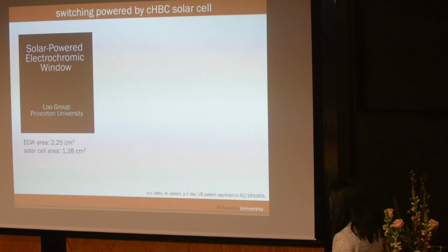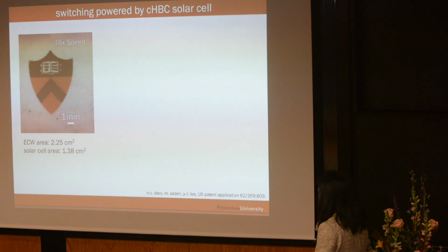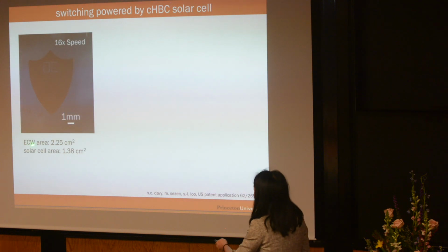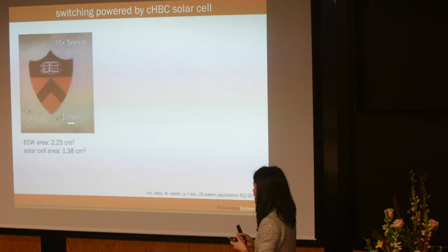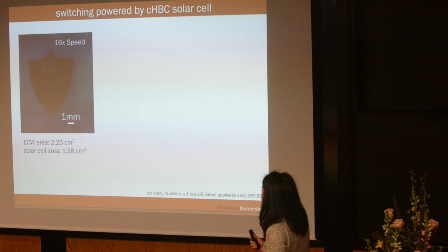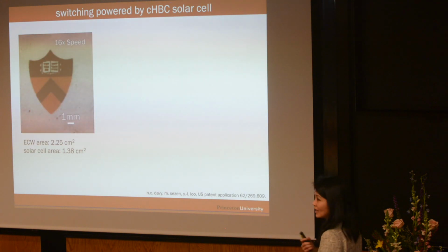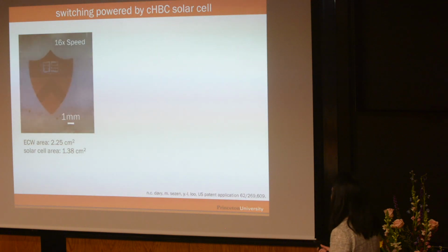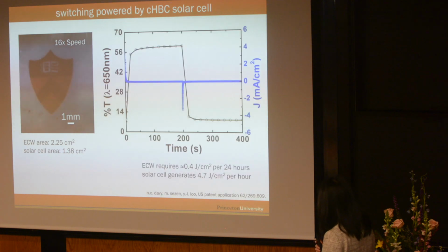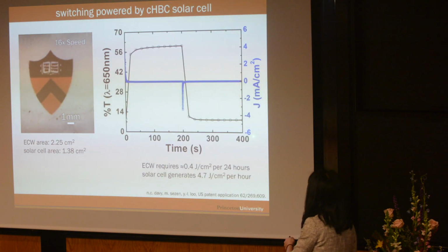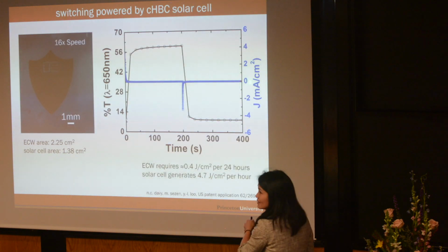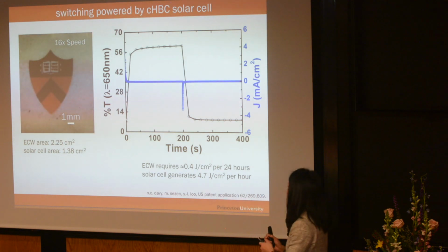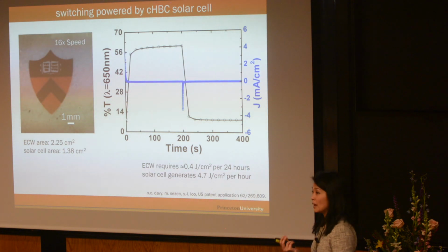This is to show you the electrochromic window that's powered by our solar cell. Here the electrochromic window is 2 centimeters, and the solar cell is about 1.4 centimeters, and you can see the switching. We've enhanced the speed so you can see the switching more clearly. This shows transparency as a function of time and the current that's required. From these kinds of curves, we can calculate the energy requirements.